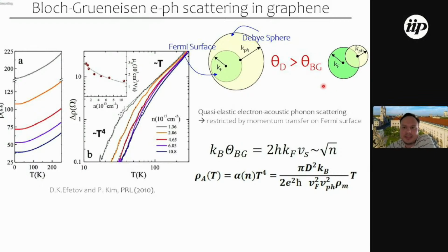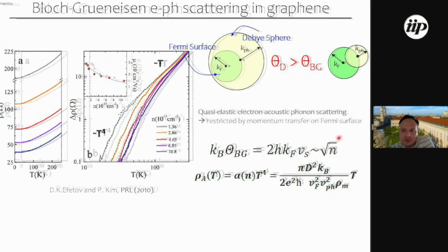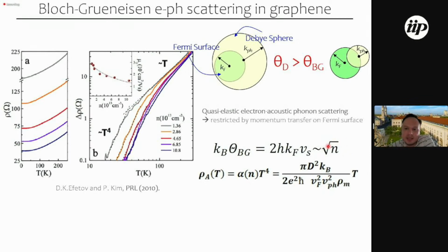This is really extremely high temperatures. But in graphene, we have the peculiarity that the Debye temperature is actually not defining the scattering process, but a reduced so-called Bloch-Grüneisen temperature, which is characteristic for this process. And this Bloch-Grüneisen temperature is directly proportional to the size of the Fermi surface. Because in graphene, we have extremely small Fermi surfaces because it's a semi-metal. Usually Fermi surfaces are much smaller than the size of the Brillouin zone. Only a few select quasi-elastic processes between electron-phonon scattering are allowed. And this Bloch-Grüneisen temperature effectively restricts these processes from happening and allows only low energy phonons to partake in that process. And so this Bloch-Grüneisen temperature is therefore proportional to the size of the Fermi surface, and therefore directly proportional to the carrier concentration in the graphene.